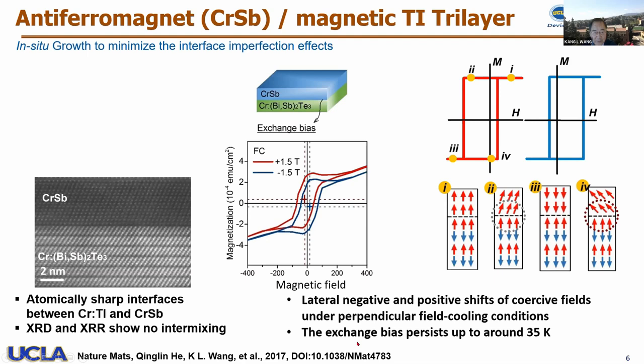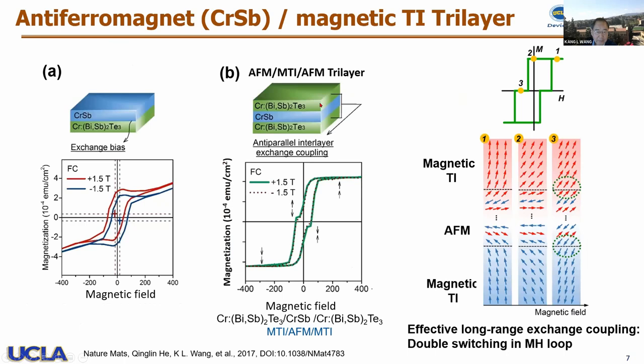Now if you grow another layer on top, it turns out you can switch from a ferromagnetic bilayer to antiferromagnetic and back to ferro again. This can be explained by AFM coupling through long-range coupling through the AFM, which is substantially thin in this case. Tracing from layer one to two to three shows this coupling effect clearly.